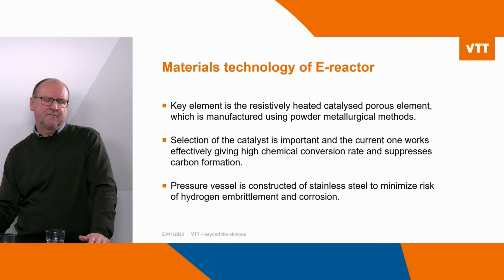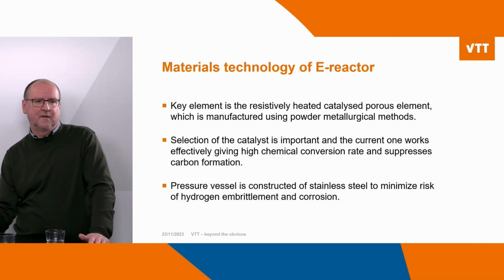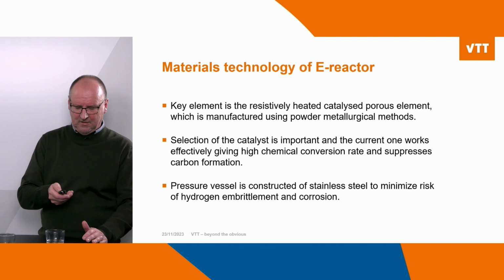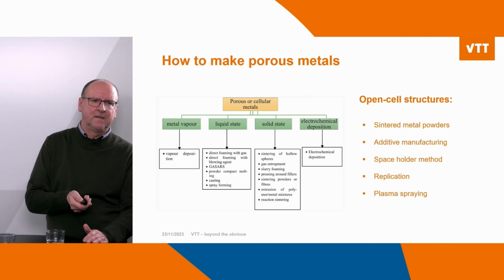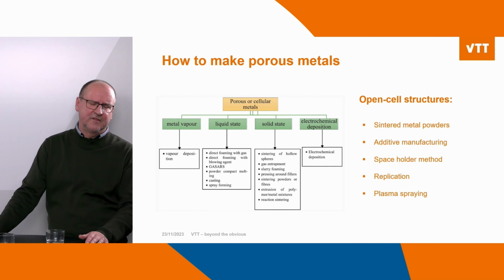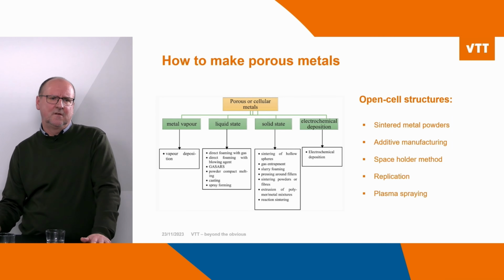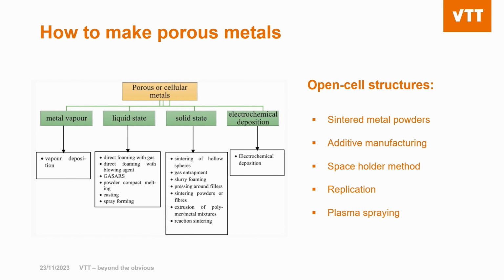But normally this is a pressure vessel, our current reactor type, and that is constructed from stainless steel to minimize the risk of hydrogen embrittlement and corrosion. So nothing special here. This figure shows that there are plenty of different technologies to make porous materials, but in our case we need open cell structures, and we have used some of those technologies, for example, to make our element for the reactor.